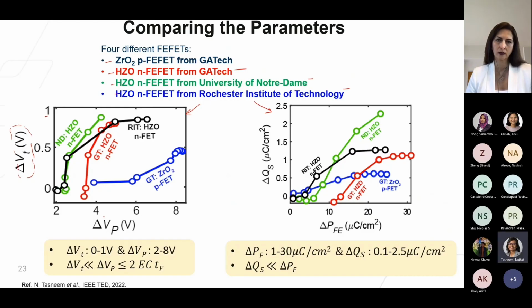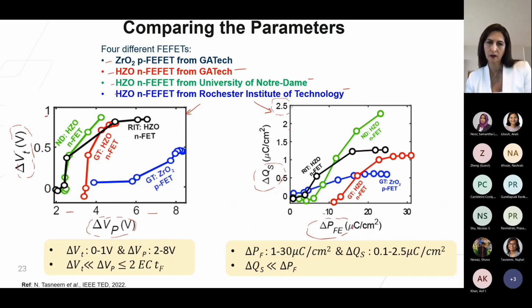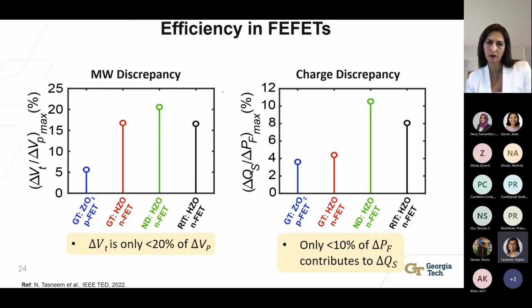On the other hand, the theoretical memory window delta VP ranges from 2 to 8 volts for all 4 of the devices. Now, this memory window discrepancy arises because of the weak coupling between the ferroelectric charge and the semiconductor channel charge. So the figure here shows that the ferroelectric polarization charge ranges from 1 to 30 microcoulomb per centimeter square, whereas the semiconductor channel charge ranges from only 0.1 to 2.5 microcoulomb per centimeter square. The figures in the next slide also show the same results.